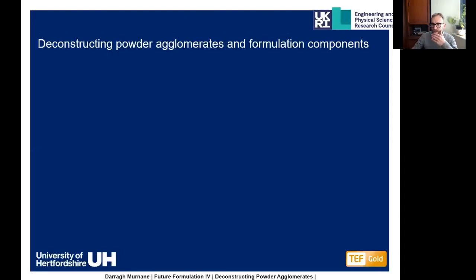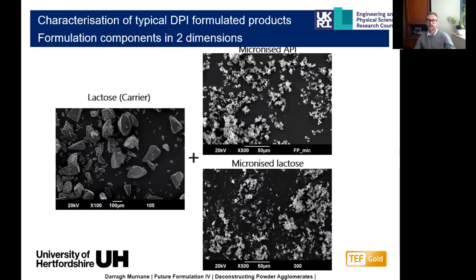So that's the major component of the formulations, which is the carrier or the diluent lactose materials. But we also then, within our powders, have agglomerated material, and there are multiple formulation components. So if we think about our typical formulation components, and really up until our program, the only way in which we were able to image the materials that were present and pull out information on their shapes and connectivity was in 2 dimensions using scanning electron microscopy.